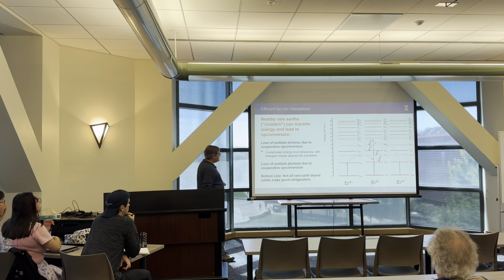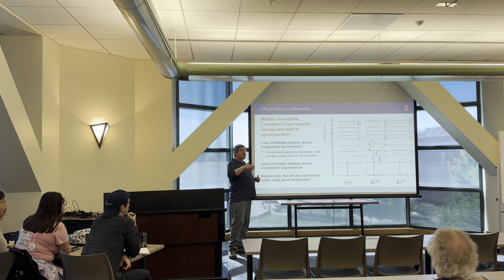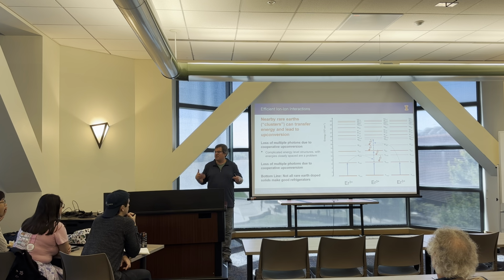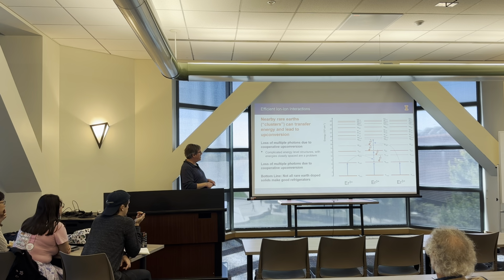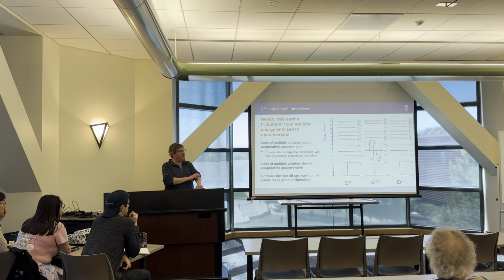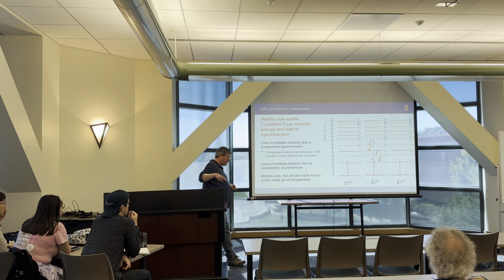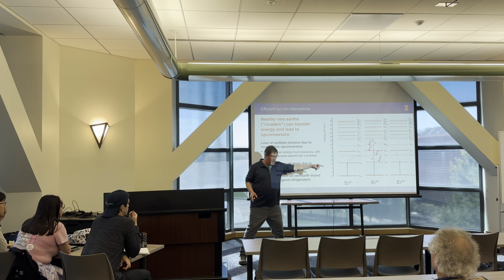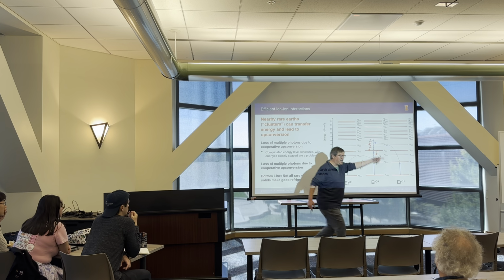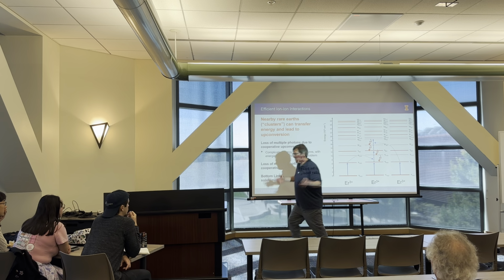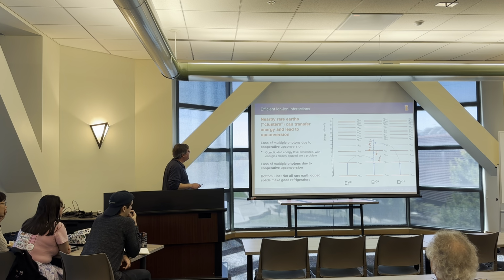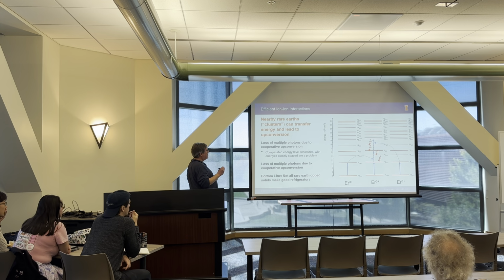Other rare earths, ytterbium, as it turns out, has a pretty high solubility in most materials. You can put a lot of it in there before it starts to quench. Rare earths will also tend to cluster because, even in crystals, you don't ever get exactly this many lattice constants before an ytterbium, and then this many lattice constants. It's whatever it happens to be. But anyway, there are cooperative upconversion effects.